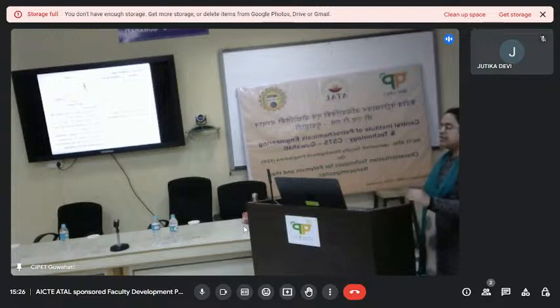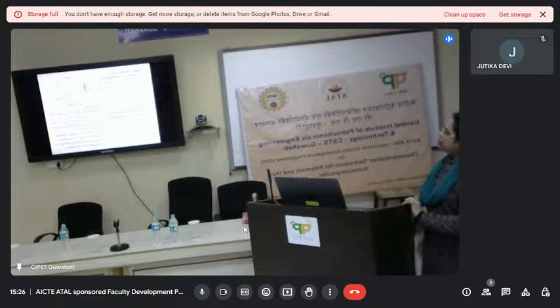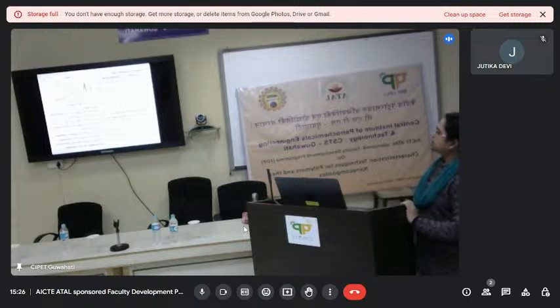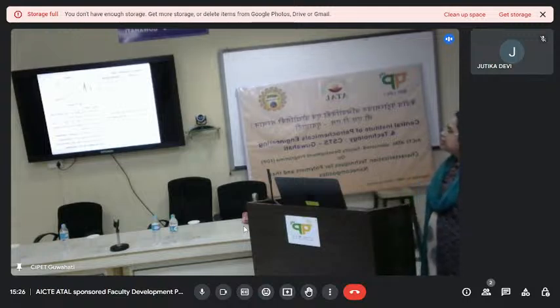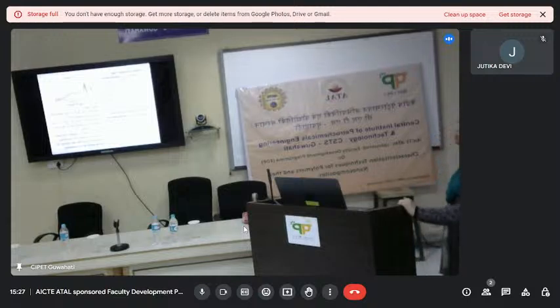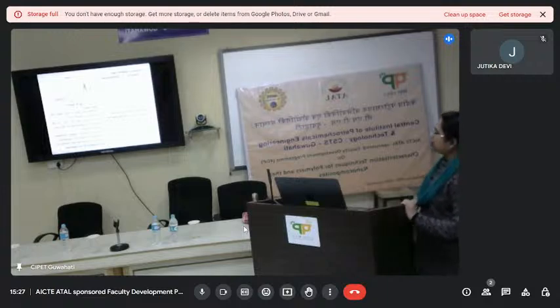So whenever it is covering the whole band gap, we call it the band edge emission. These results I have already listed here. The absorption edges are blue shifted with increase in concentration of PVA. From that we know that the sizes of the nanoparticles are getting reduced with increase in PVA concentration, and the effect of quantum confinement increases with increase in PVA concentration, and the position of band edge emission also gets blue shifted with